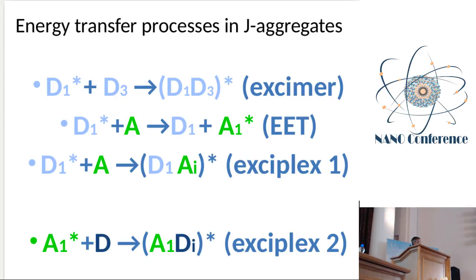So we can describe the energy transfer processes in the mixed solution by different equations, which represent formation of excimers, simple exciton energy transfer from the donor J-aggregate to the acceptor, and finally formation of exciplex when the energy of G aggregates of the donor is transferred to some species of the acceptor molecules. And the similar process can also be described when we excite acceptor J-aggregates, which also can transfer energy to donor species and form exciplex of the other type.